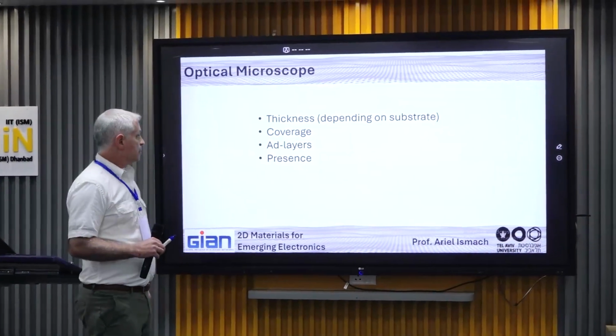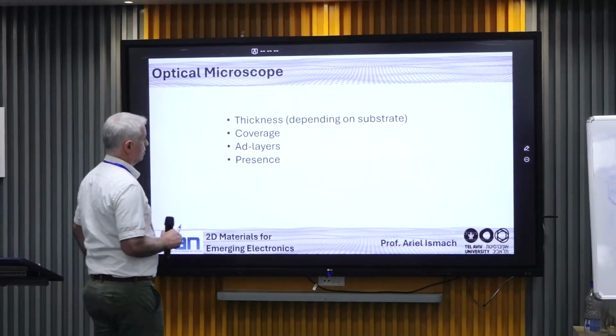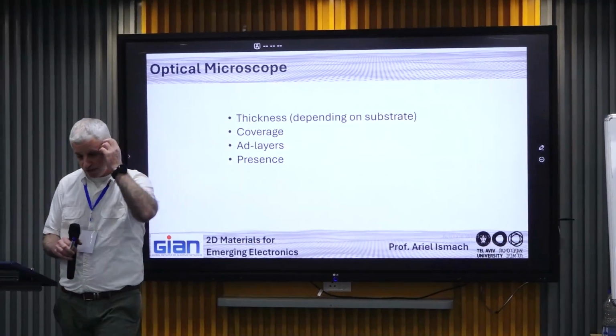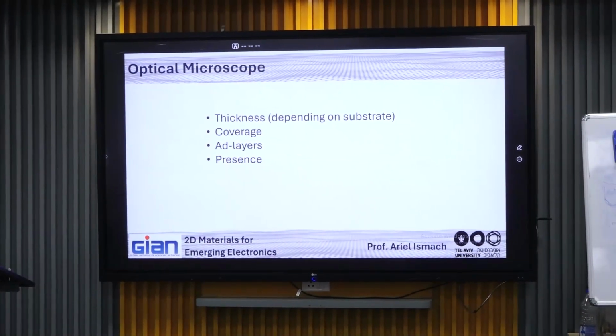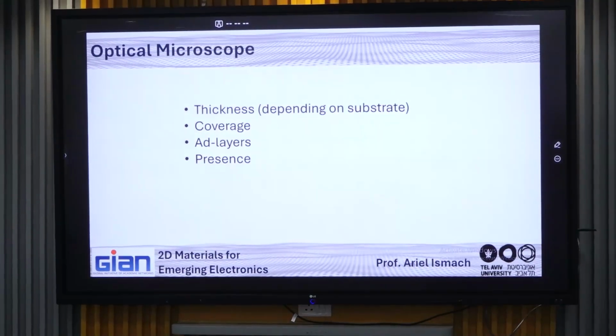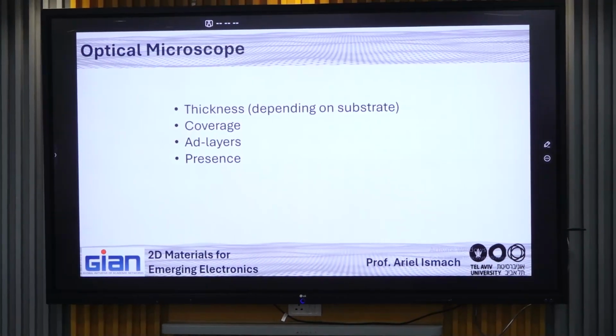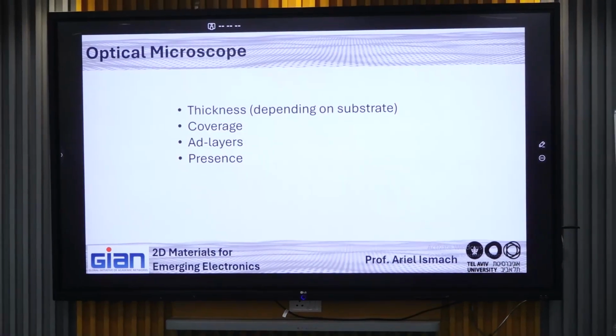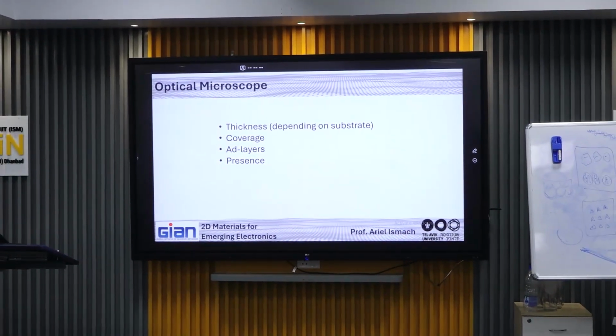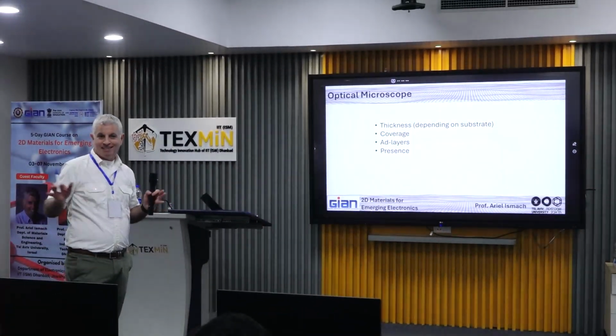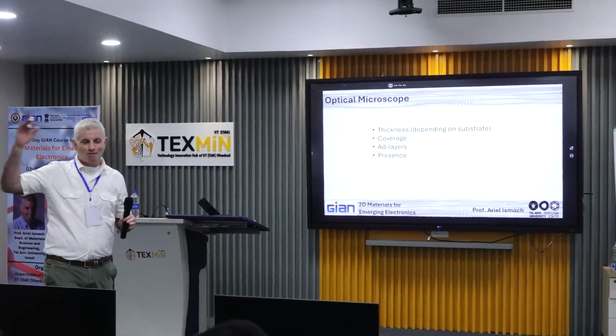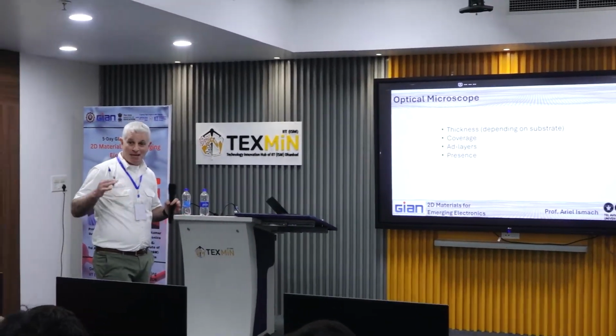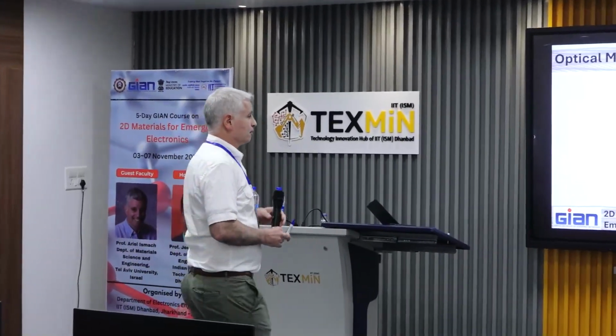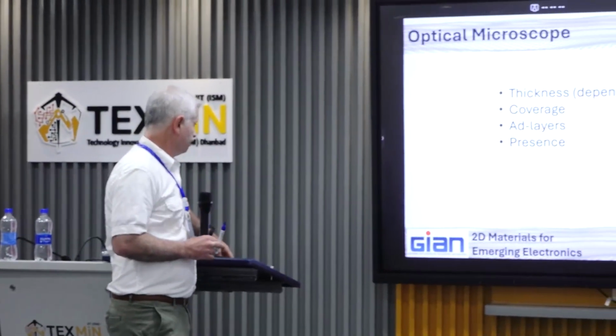So therefore, the optical microscope is very good for thickness, which depends very much on what substrate, if it's silicon or other, for coverage, for ad-layers, and of course just the presence. This sounds trivial, but anybody that deals with growth, especially with the growth of something new for the first time in the lab, needs to check that they are getting the material. That's the first question. Am I getting the material? Not how good is it, how large is it. Am I getting the material? This is the first question, right? So this can answer that very fast.